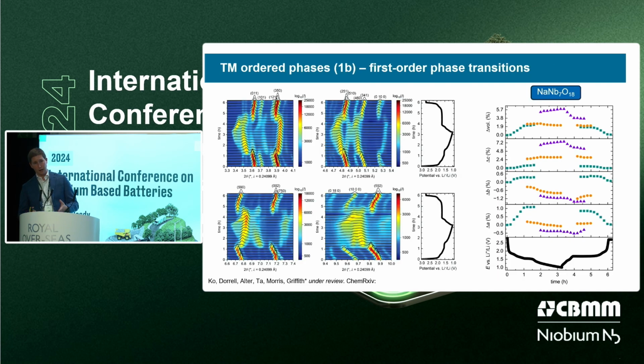Okay. Now, very recently, days ago, we are showing something that in some sense confirms what we've been saying, which is that if you don't have transition metal disorder, so we're looking here at NaNb7O18, the sodium doesn't sit on the same site as the niobium, so it's irrelevant in terms of that transition metal ordering. It's all niobium, if you will. And so we see these very stark phase transitions. You can see throughout this, we actually have a second one that is more subtle, a smaller phase transition.